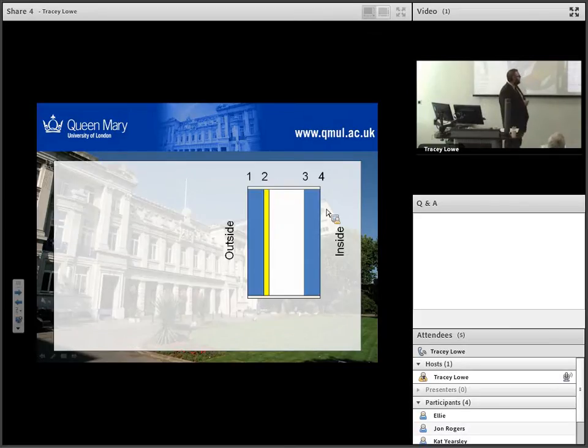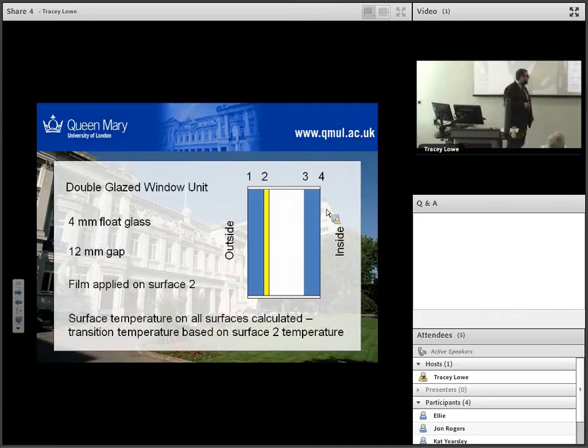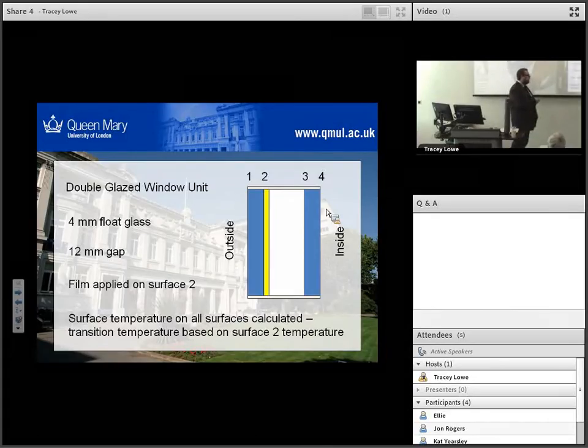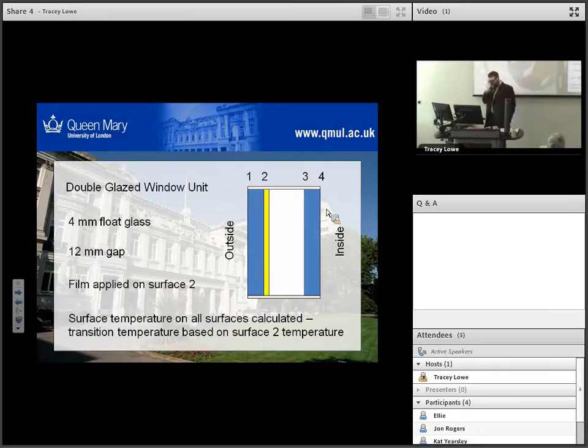Our model is also like this kind of thing here. We're looking at a double glazed window unit, standard 4mm float glass with a 12mm gap, filled with just air. Our vanadium dioxide film is put on surface 2, so that's the inside surface of our exterior pane. We're going to base all of our transitions and changes on the actual surface of that piece of glass, which is something not everyone does. It can be a little bit misleading.